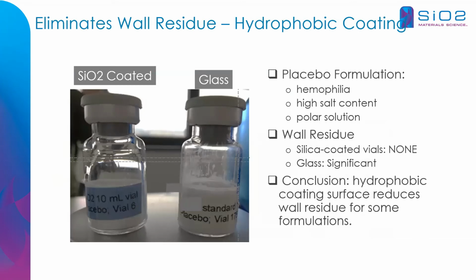Again, as I mentioned before, because SiO2 containers have a hydrophobic drug contact surface, there is very little hang-up of the liquid during freeze drying, and so you don't have any residue that gets freeze dried on the side wall. You can see a comparison of a study that was done. It was a placebo with hemophilia, high salt content, and so it was one that was prone to hang to the wall in a hydrophilic environment.